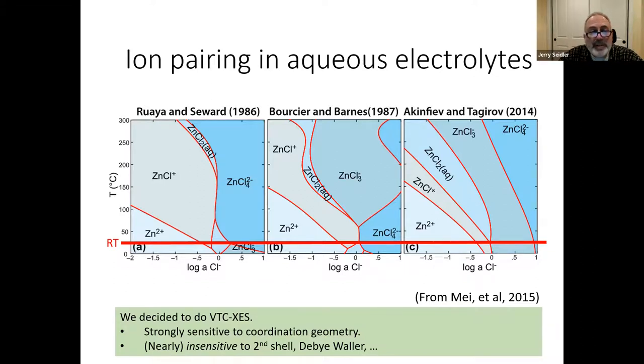So we decided we would do valence-to-core XES. There'd been a fair amount of XAFS on these systems already. And they're very tricky to interpret because of the large role of the second coordination shell. Whereas here, we only really want information on the first coordination shell. So we said, okay, valence-to-core XES should be strongly sensitive to coordination geometry and nearly insensitive to the second shell.